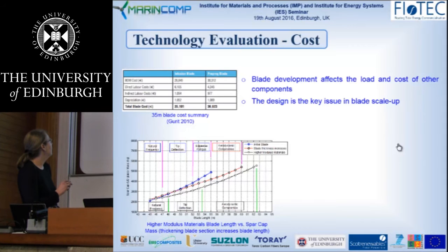For the E-glass composite blade, blade length can go up to 55 meters, after which they become unfeasible. Up to 47 meters the design driver is natural frequency, while from there to 52 meters the design driver is tip deflection, and beyond that it is edge fatigue. If we make the airfoil thicker we have to make an aerodynamic compromise, but we are on the safe side structurally. Introducing higher-modulus materials allows us to go beyond 62 meters.